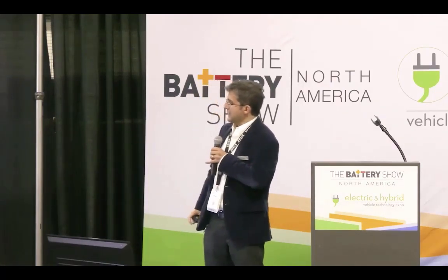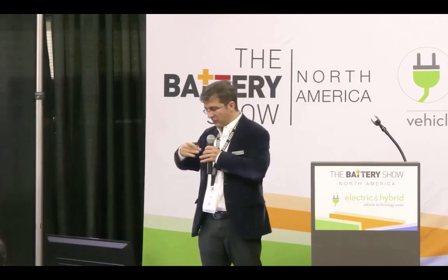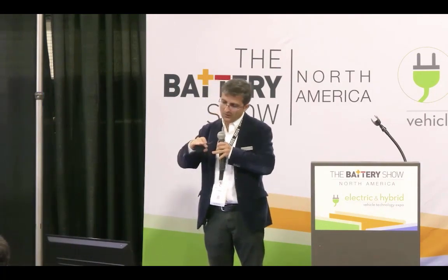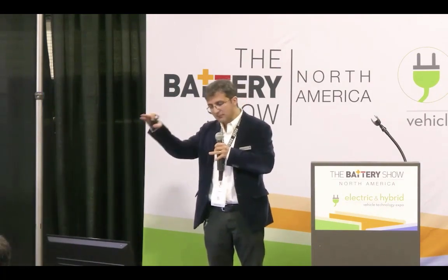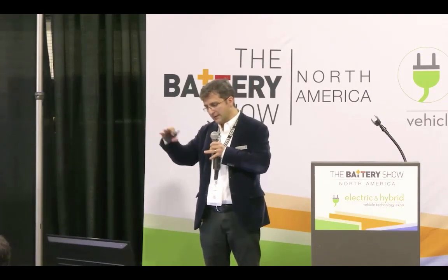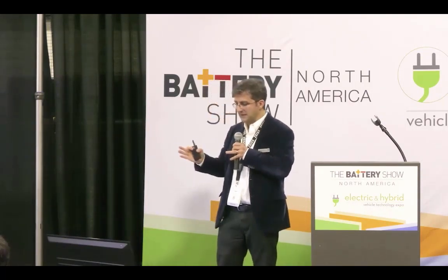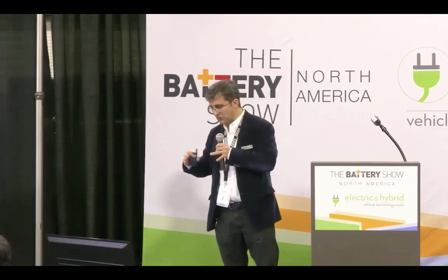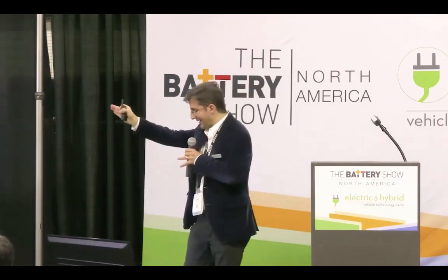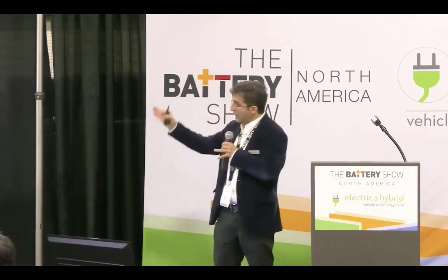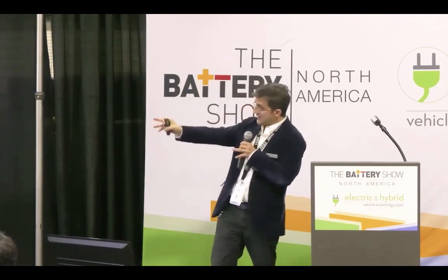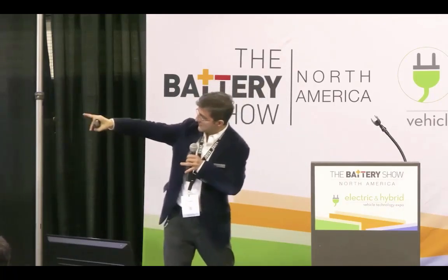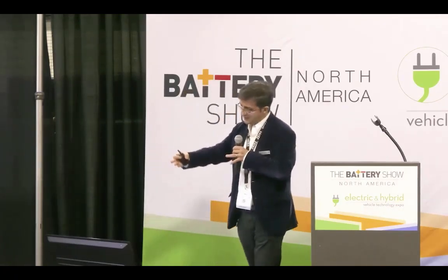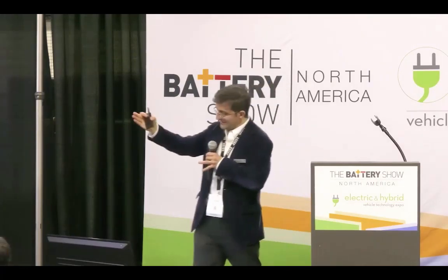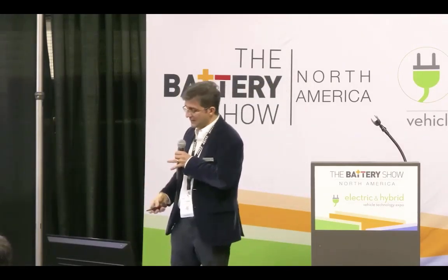For checking more fully assembled batteries, you can check not only the battery materials, but also the assembly, like the aluminum or steel materials that you have in the casing. So you can check the collecting tab, you can check some porosity on that, you can check the traditional overhang measurement, the housing, the welding of the final product, the lamination in the battery, deflected anodes, as you can see there, particle inclusions that you are not expecting, the electronic components that are inside of the battery, and any other type of cell defects.